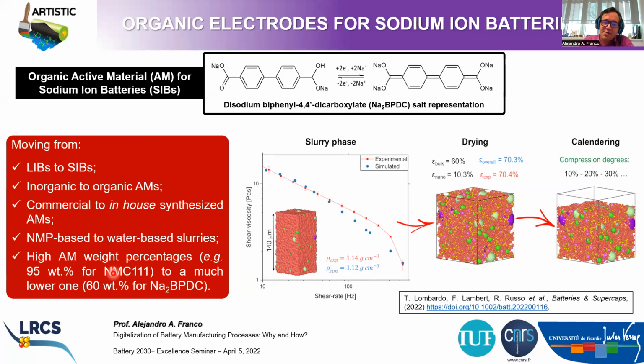And what we did is we characterized experimentally the viscosity as a function of applied shear rate. We fit the calculated viscosity with the coarse-grained molecular dynamics model, representing this collection of active material particles and CBD containing carbon additive, binder, and solvent. Then, once we get this good fitting, we perform the simulation of the drying process. We shrink the CBD size, then the electrode structure forms. And then we fine-tune the parameters in order to recover the experimental porosity. You see that the simulated one is 70%, and the experimental is also 70%, more or less.